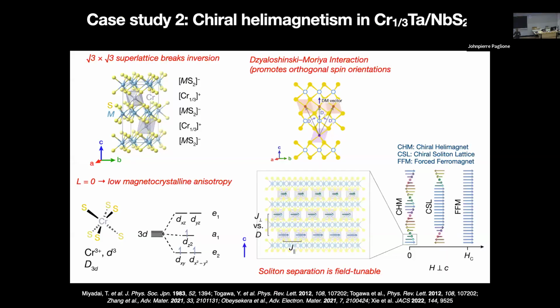And so to understand how the symmetry of these superlattices can affect the magnetism, I want us to consider the chiral helimagnets, which are these chromium 1/3 tantalum and niobium disulfides. So we'll look at the chromium 1/3 niobium disulfide and the chromium 1/3 tantalum disulfide and compare their magnetic structures, their phase diagram, and what we've learned about these systems. So in these systems, with the 1/3 stoichiometry, you have this square root of 3 by square root of 3 superlattice, which is non-centrosymmetric.